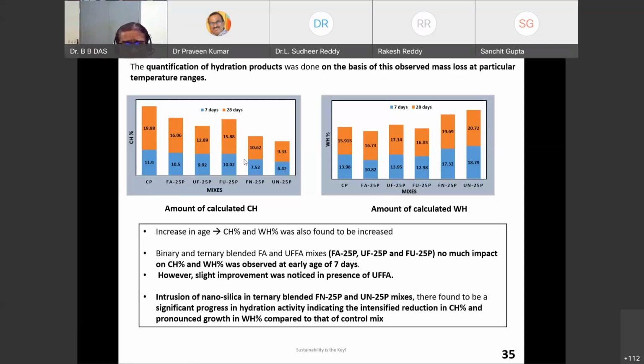So you can see here, by infusing a very small percentage of nanoparticles in the cementitious matrix, I am able to drastically reduce the percentage of calcium hydroxide and thereby strengthen the system, strengthen the cementitious composition. Okay, now come to the amount of calculated WH. WH is, as I explained to you, the percentage of hydrated water except the CH. And I was telling you, most of the hydration products, if you deduct CH, mostly it will be the calcium silicate hydrate. But we cannot designate it only CSH, remember. That's why we designate it as WH.